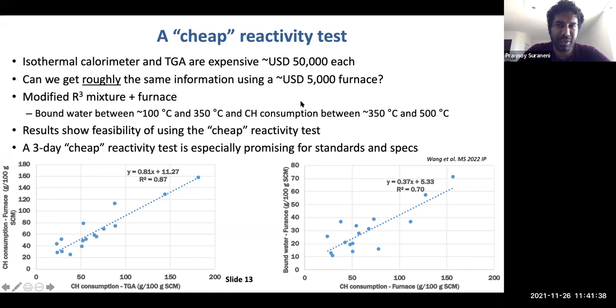When you're reducing the test cost 20 times, you're not going to get data as nice. This is true. There is a little bit of scatter. The values are not as nice as they are when using a TGA, but it's not so bad, right? We are getting largely the same amount of information, and we can actually do similar levels of classification by plotting bound water versus calcium hydroxide from the furnace.